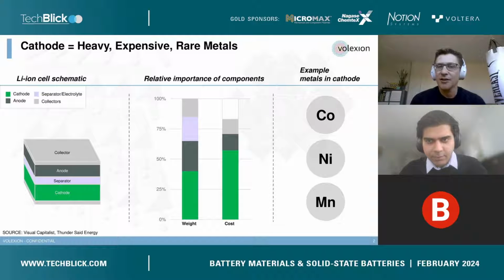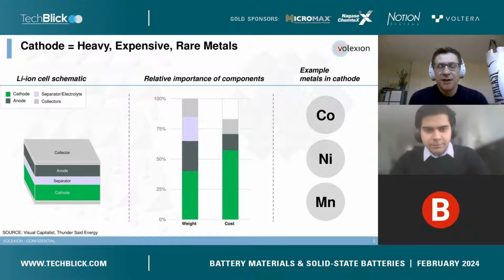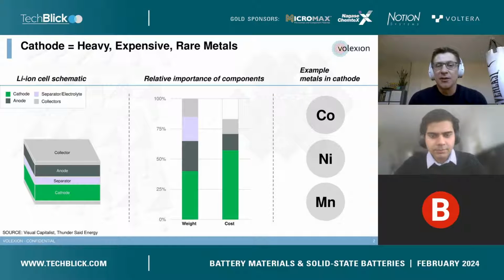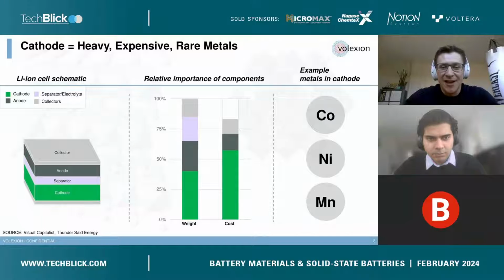And so why does the cathode matter? Well, when you look at a weight breakdown or cost breakdown of a lithium-ion battery cell, the cathode generally accounts for 40% of the weight of a cell, and on top of that, it also accounts for up to 50% of the cost of a lithium-ion battery cell. In addition, the cathode pulls a lot of constrained materials for which the supply chains are global and challenged. So, for example, that's where you find the cobalt, the nickel, the manganese. So in summary, the cathode is expensive, it's heavy, and it has metals that need to be harvested across the globe. So we think it's worth looking at this material and using our technology to improve the cathode and get to the next level of performance.